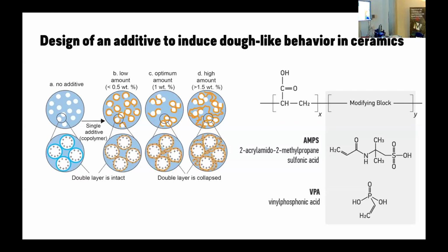It is not a slip casting solution. I don't know if you are familiar with this, but if you have, for instance, alumina, you mix it with water, you have this alumina suspension, and that's a slip system, right? You basically pour it into a mold. Usually that's how toilets are made. You have the toilet-shaped gypsum mold, which allows the water to evaporate from the system. That's a slip casting system. We don't want this. We want something that we can shape. Either we can push it into a mold, or we can directly put it into a machine. So it cannot flow. That part is important, right? I am trying to make a system that doesn't flow.